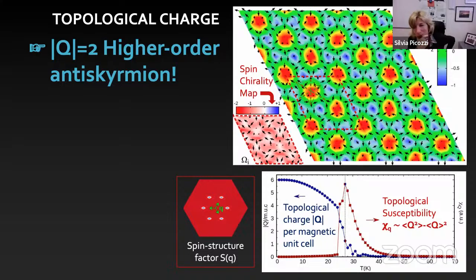Yeah, we changed the U, and what we could infer was that, of course, the absolute values of J1 and J3 do change. What we convinced ourselves about is that the ratio doesn't change so much. So, for example, the off-diagonal to diagonal pretty much stays there. So this is why we didn't worry so much about the physics.